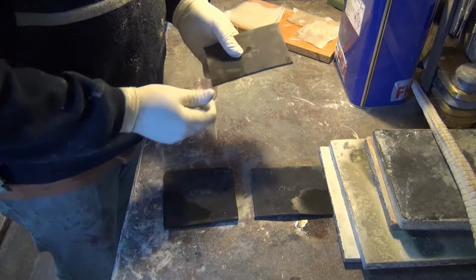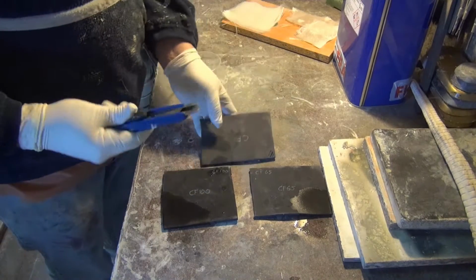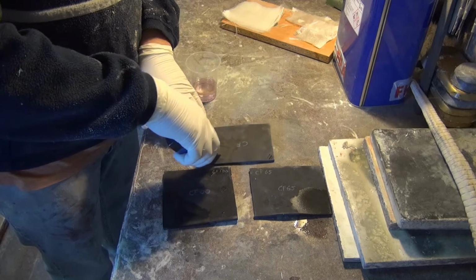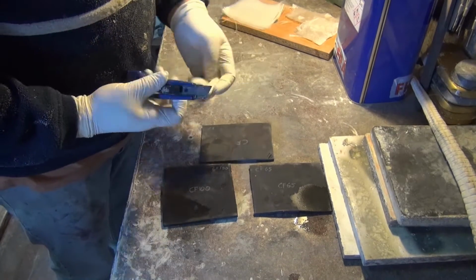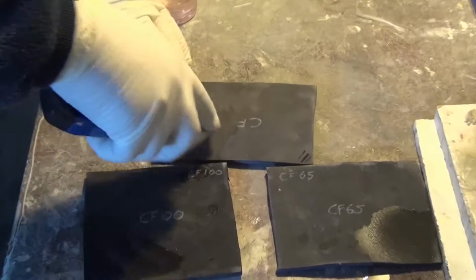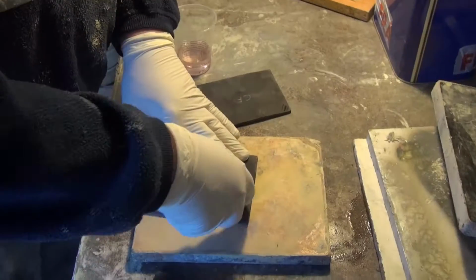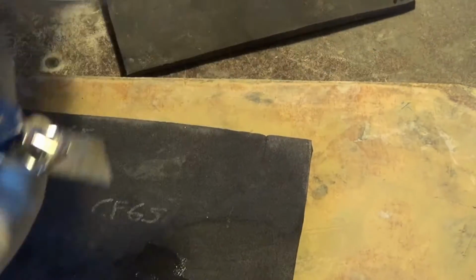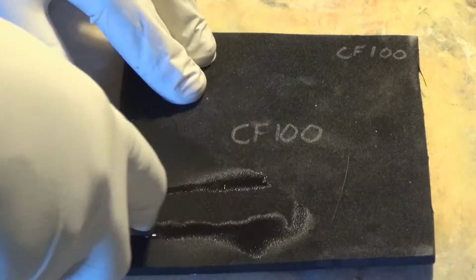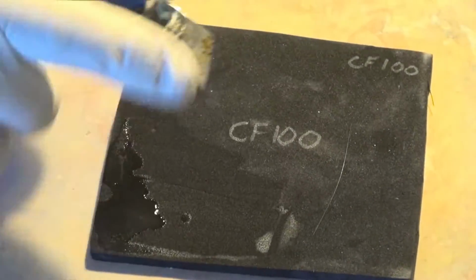To see if the samples react to the acetone, we use the unsharpened part of the blade. When we scrape the samples, we verify that they are not altered in any way when in contact with the acetone. All three samples, the craftfoam, CF65 and CF100, absorb a little amount of acetone, which is expected because it's a porous material.